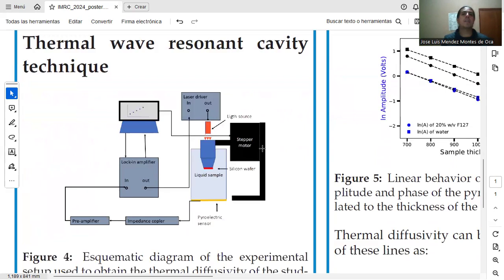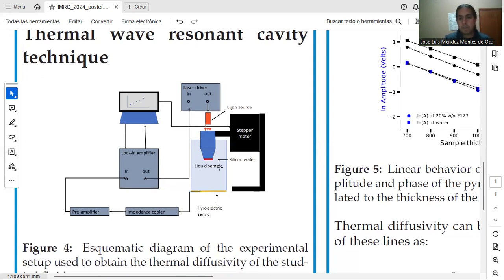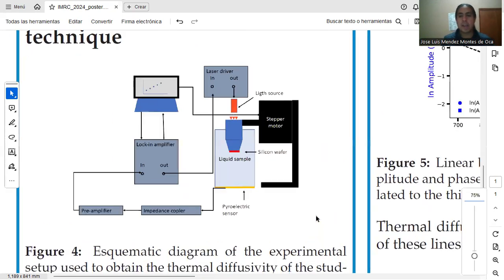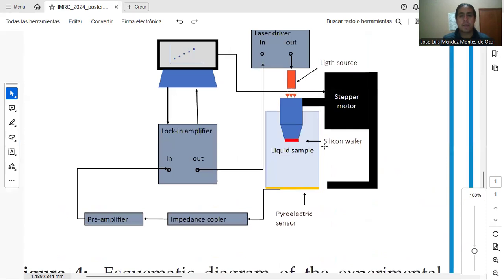For this reason, we use the thermal wave resonant cavity technique, which consists in sending a sinusoidal signal from a lock-in amplifier to a laser driver to generate a light source with a well-defined frequency. And this electromagnetic radiation is sent to a silicon wafer, which acts as a thermal generator. And so it converts the radiation into differences of temperature.